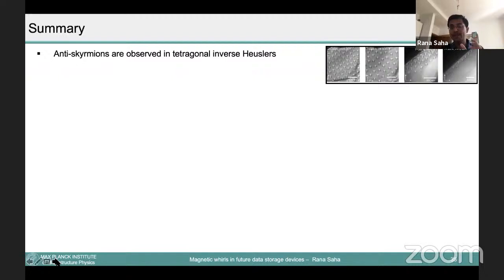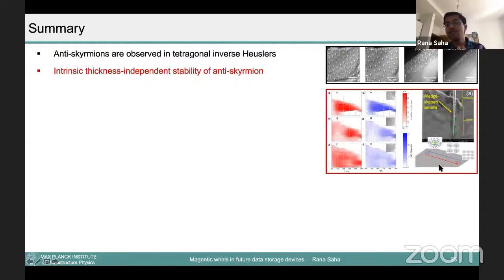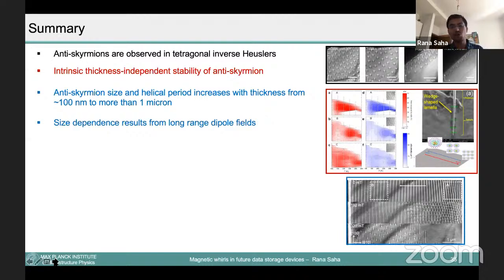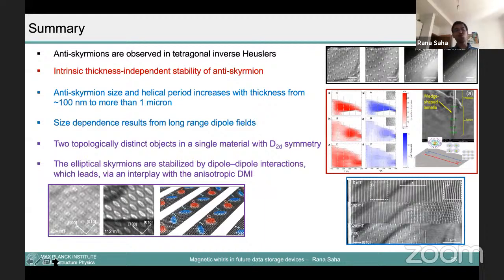Okay, so let's summarize my talk. I showed you that we have observed antiskyrmion using transmission electron microscope images. These are real images, and we have seen it is very important to know the stability. In a thinner region, you have a larger number of skyrmions. In a thicker region, you have larger skyrmions and less density of skyrmions. And you can actually tune the size of the skyrmion to have a higher density, and more data can be retained there. And also we have shown how it is possible to make antiskyrmion and skyrmion in one material, and you can actually have a racetrack out of this.